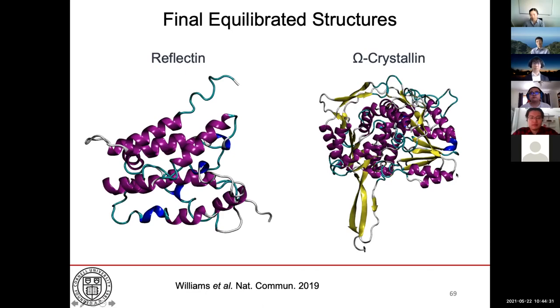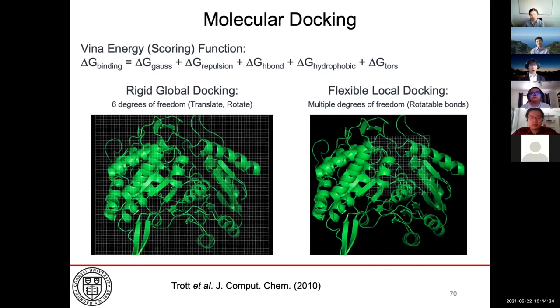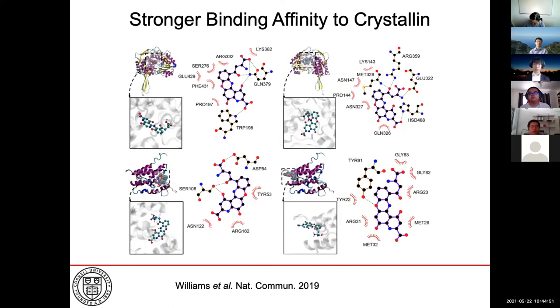To verify this, I performed molecular docking simulations, where the premise is, of course, to minimize an energy function. I perform global rigid docking with limited degrees of freedom to search for potential binding pockets, and then I perform flexible docking in the local region with multiple degrees of freedom. From these docking results, we found stronger binding to crystallin than to reflectin. And intuitively, the reason is very apparent, right? The pigment molecule docks in deep pockets within crystallin and therefore is able to form very elaborate networks of hydrophobic interactions given by the eyelashes and polar interactions given by the lines. In contrast, the pigment molecule docks very superficially onto the surface of reflectin, and the network of interactions is therefore much less elaborate.